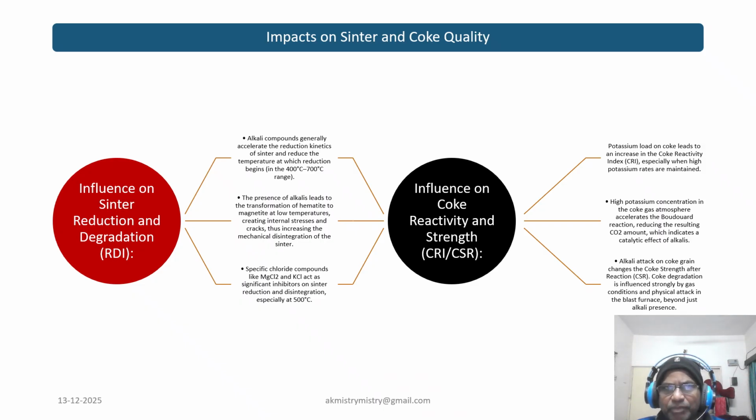The second thing is that these chlorides, especially magnesium chloride and potassium chloride, act as a barrier to this reduction and disintegration, particularly in the band of 500 degrees centigrade. This makes the entire system more complex.